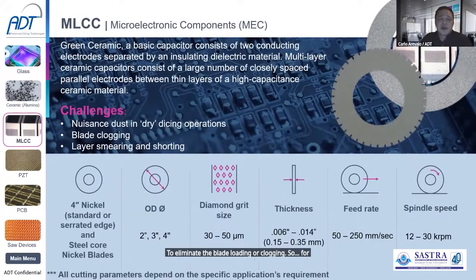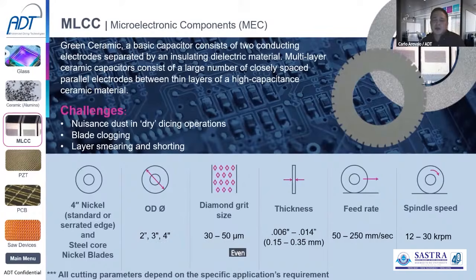So for this particular nickel blade, it can be made for 2, 3 or 4 inches. Diamond grit size would range similar to the other ceramic applications, 30 to 50 micron. Thickness range from 150 to 350 micron is available. Feed rate is relatively high considering this is dry dicing, but this is a very soft, green ceramic, so you can cut it very fast. The issue is mostly on the dust or other processes. But in terms of quality, you could cut it at high speed, even at 250 millimeter per second. Spindle speed depends on the blade size again, and can range from 12 to 30 kRPM.